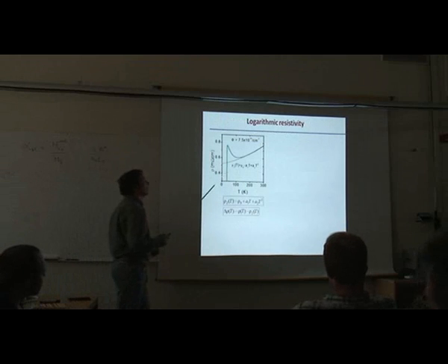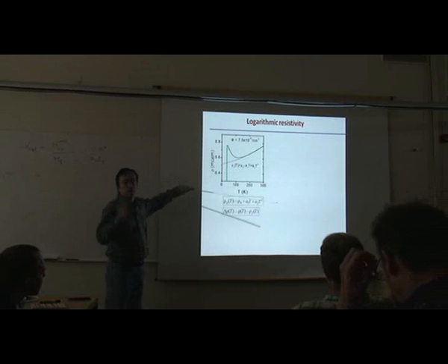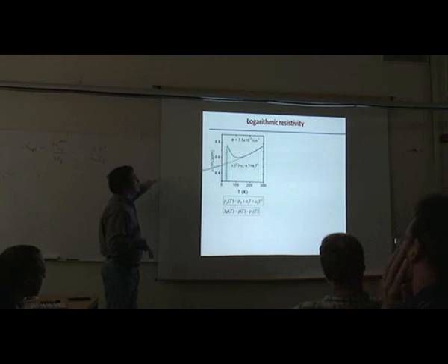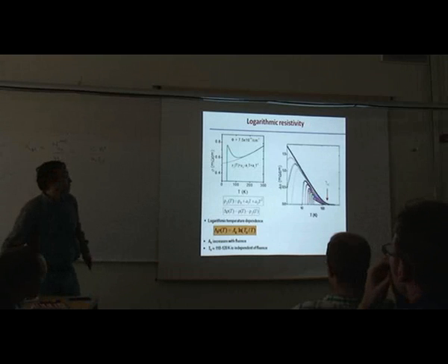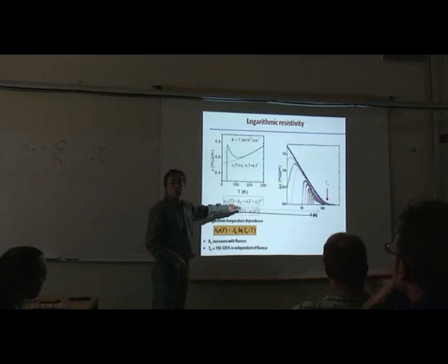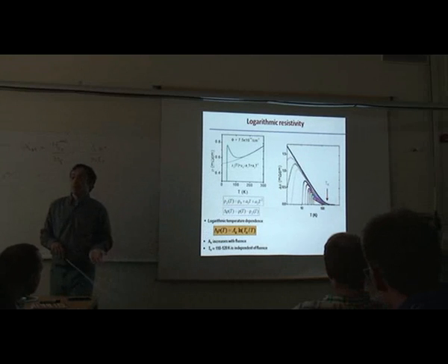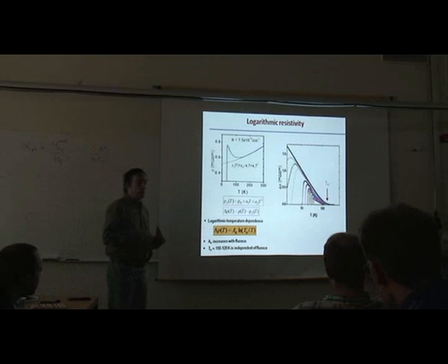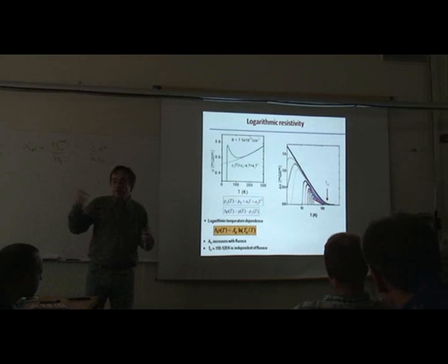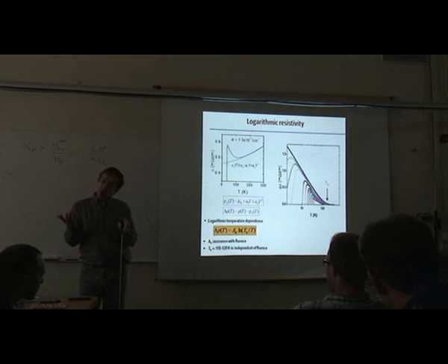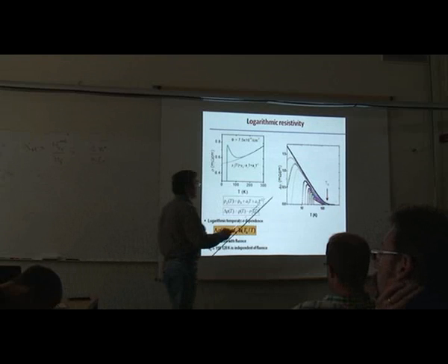Now we did a simple analysis. So this is one of the resistivity curves. What we did, we fit this part with a quadratic polynomial, like in the conventional Fermi liquid, and then this extra was analyzed separately. If you plot this extra in a log scale, we have a straight line, telling us that this delta rho is simply logarithmic in temperature. And when we see something logarithmic in temperature, we immediately say, aha, it's Kondo effect. That is not surprising because, as I said before, radiation produces magnetic moments, so you expect some magnetic scattering. Magnetic scattering produces this logarithmic upturn, so it's all consistent. And the effect is huge.